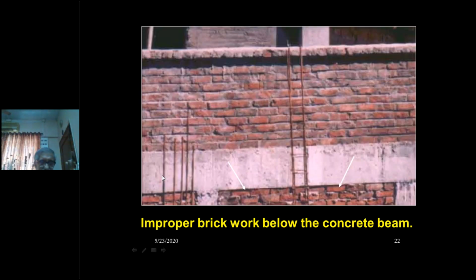Many a time there are construction joints. You see, we make an RCC framework and build the wall inside. And the wall expands and contracts in a different way than the RCC framework. And therefore, you have separation cracks. Now, many a time the wall is not constructed properly from the outside. So there are obvious large separation cracks appearing and allowing even leakage of water inside during the monsoon, because there are lots of gaps left, and hurriedly done plaster from the outside, maybe in only a single coat, without first sealing all these joints.